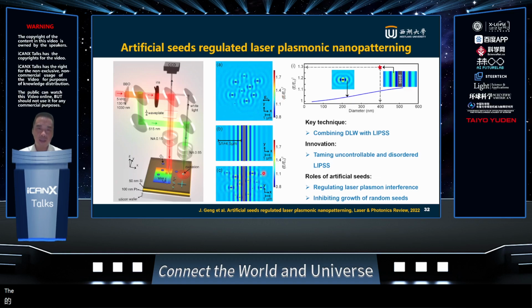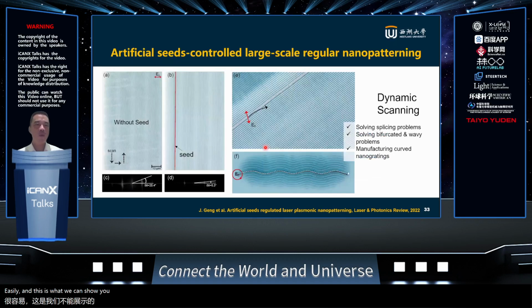These gratings will still propagate. And of course, when we truly prepare the samples, we will try our best to remove these nanoparticles, though you cannot remove all of them. So we use direct laser writing to make an artificial seed, and based on this artificial seed, we can start to make gratings easily. And this is what we can show you.